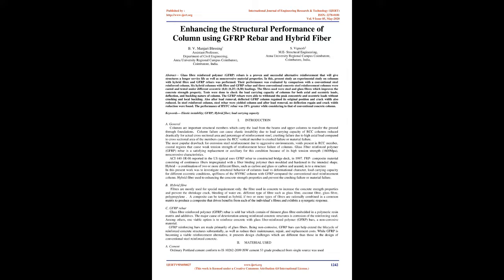The GFRP rebars were able to withstand the peak concentric and eccentric loads without crushing and local buckling. Also, after load removal, the deflected GFRP column regained its original position and crack width also reduced. In the steel reinforced column, the steel rebar yielded, and after load removal, no deflection regain and crack width reduction were found. The performance of the HYFC column was 18% greater compared to that of the conventional concrete column. Keywords: elastic instability, GFRP, hybrid fiber, load carrying capacity.